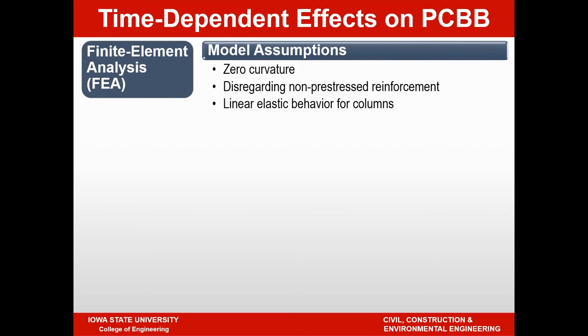During the model development, we made a few assumptions. One is that even though this particular frame is a curved structure, we eliminated the curvature and assumed zero curvature. This is to make sure the analysis can be easily interpreted and the results can be used for averaging between different bridge structures, which we were hoping to accomplish. We did not include the non-prestressed reinforcement, and we initially assumed linear elastic behavior for columns, and then we modified the elastic stiffness once we realized that the columns had cracked.